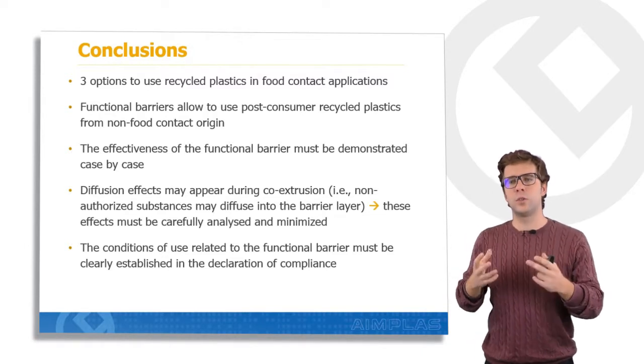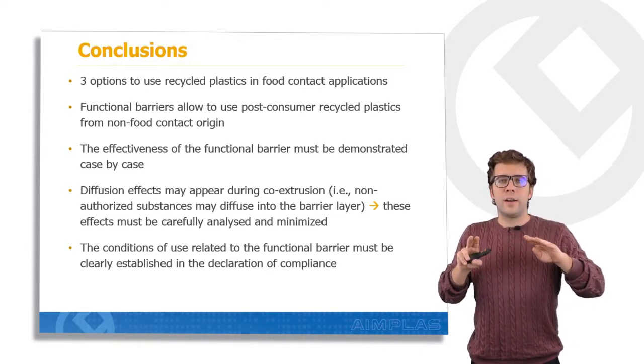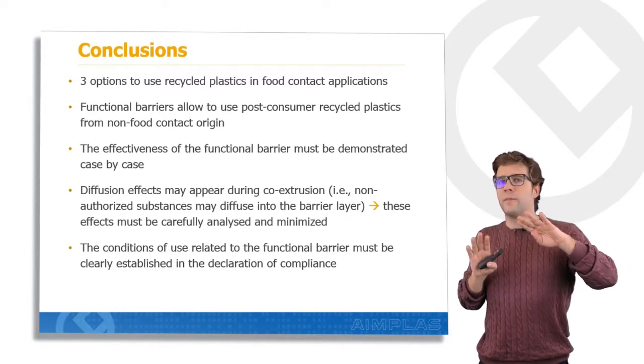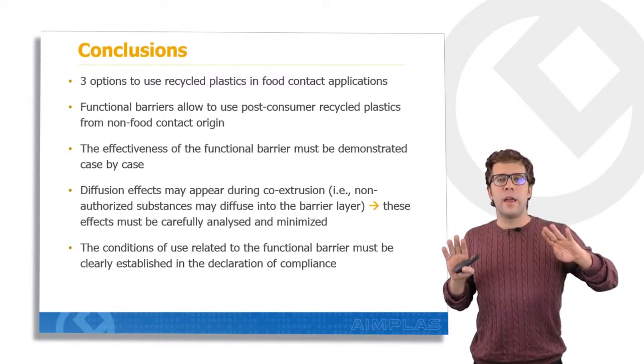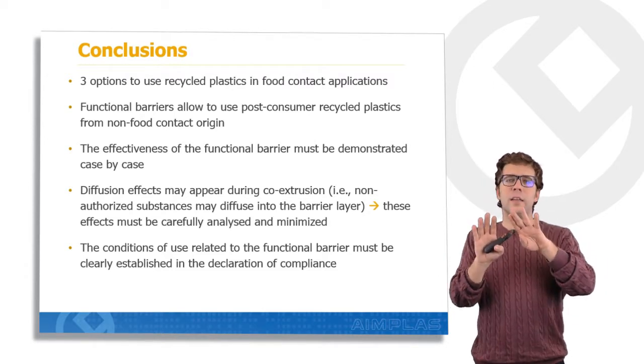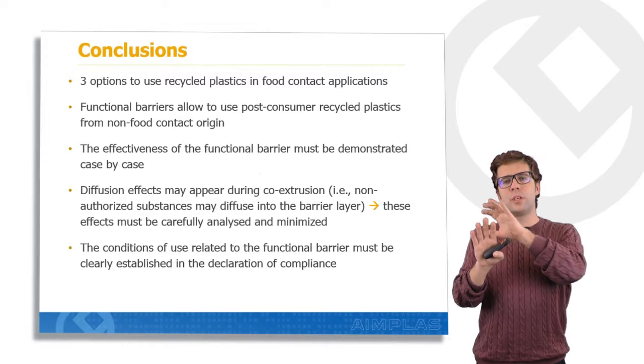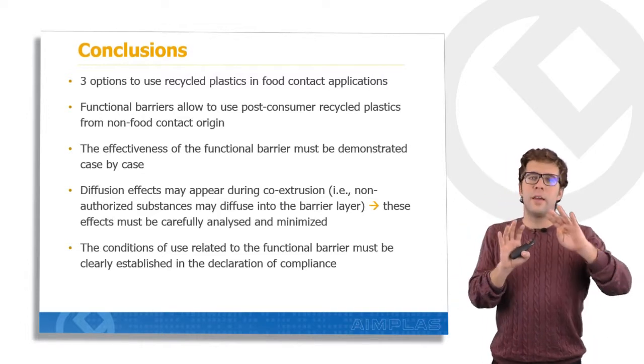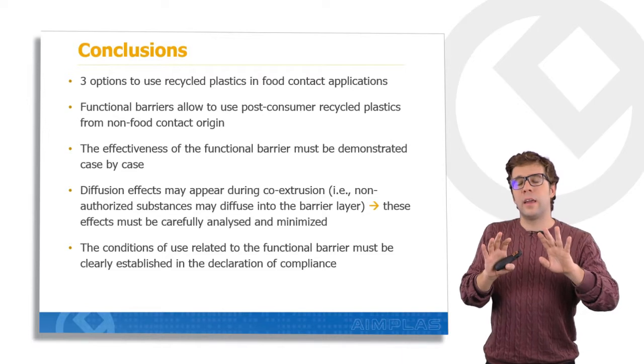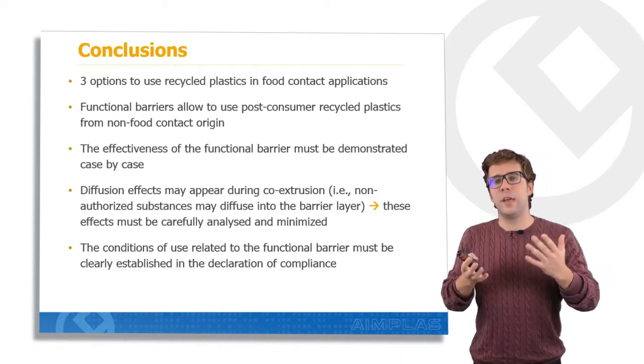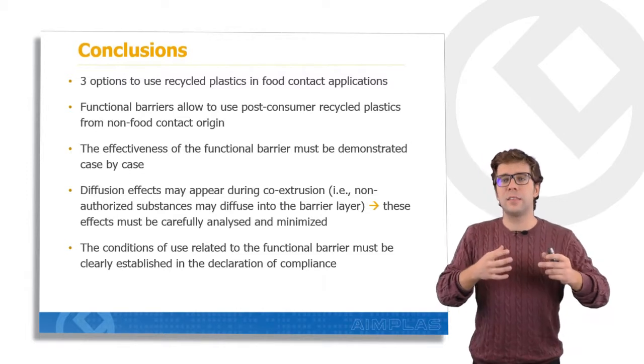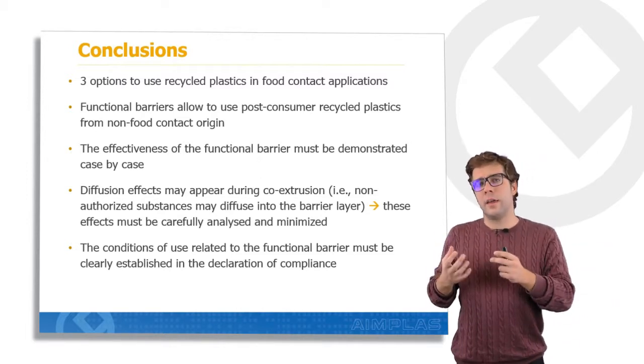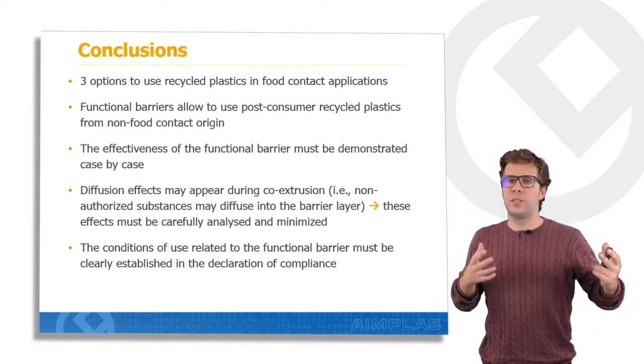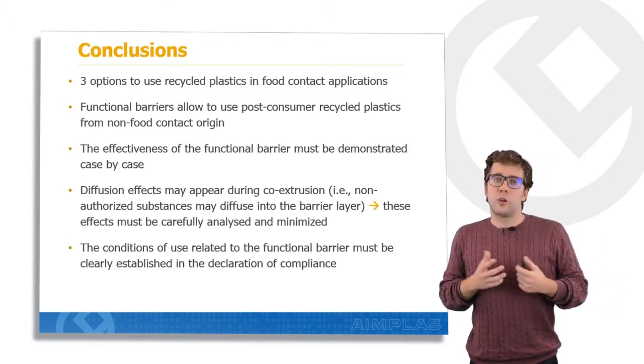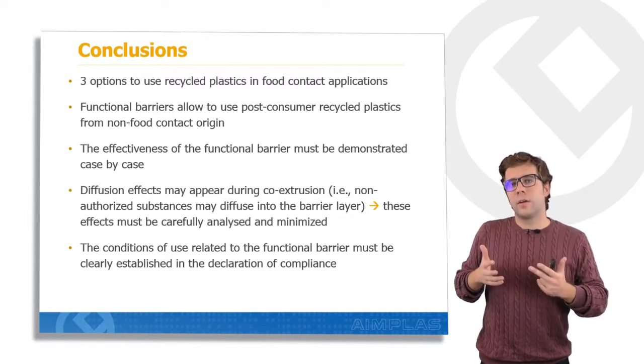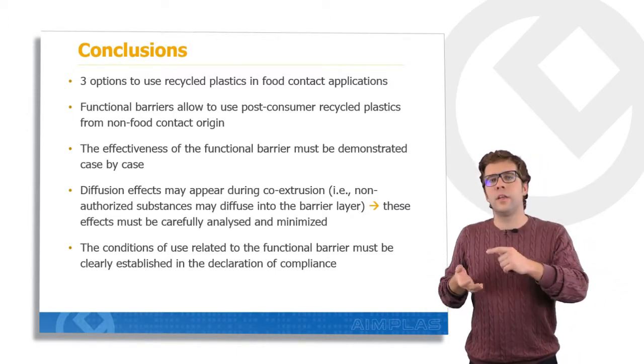In this case, during co-extrusion, there are moments where the functional barrier and the recycled layer are in a melting state, and in this case we can have some migration, some diffusion effects from the recycled layer to the functional barrier, and we must be able to analyze and minimize these effects to be able to ensure the food safety of the packaging. Also note that these kinds of effects won't appear in lamination or in injection processes.